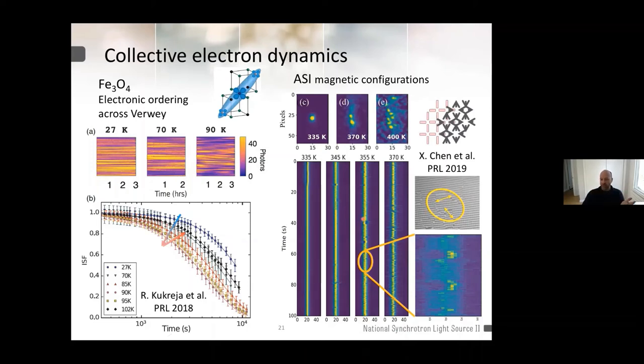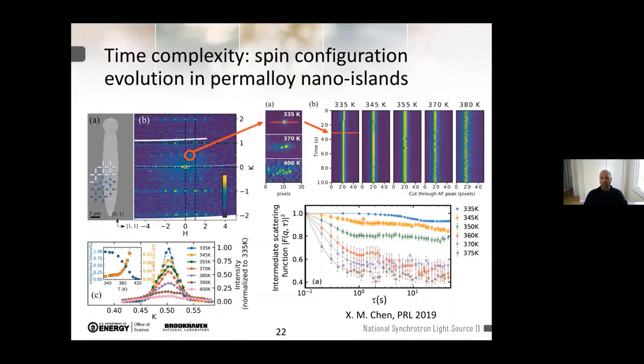Instead, here we get an average information, but it's very powerful because the Fourier transform works for us. So I use the same argument to show you that this is the lattice cell, and given that it's an antiferromagnetic arrangement, in the center of the cell you get the new magnetic information. So you know by localization exactly what you look at, and then you can check polarization, you can check energy, you can check other things, obviously. And this is the same thing that I showed before with a little bit more analysis, the intermediate scattering function in the derivation that I was proposing.